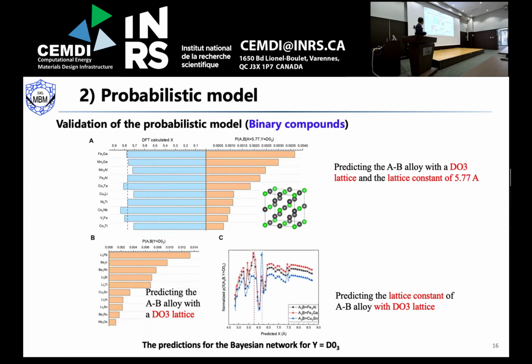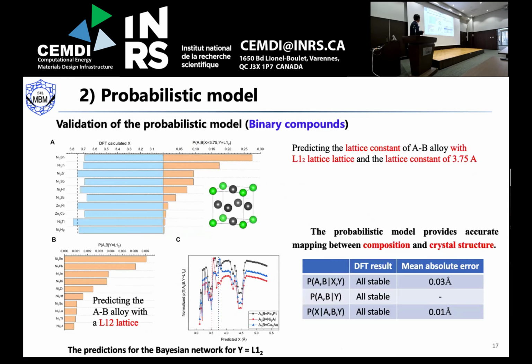And we also do the D03 structure. For the same case, you can predict them in the three cases. And we also do it for the L1-2 structure. Once you know the lattice constant and the crystal structure, you can predict the alloy. And once you only know the crystal structure, you can also predict the AB. And once you know the elements and crystal structure, you can also predict the lattice constant.